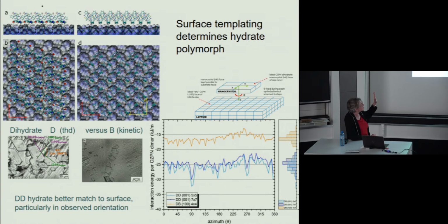And doing some calculations where you've got a perfect surface and then using a nanocrystal of the two different dihydrates above the lattice, we could show that the dihydrate D, as a function of the angle of the nanocrystal, had some preferred orientations which did match with the observed orientation of the dihydrate crystal structure on the olanzapine surface. And there's a better match going down between the surfaces than there is with the kinetic product, where the ones that were seen on the surface probably nucleated elsewhere and had just fallen down in any old position.